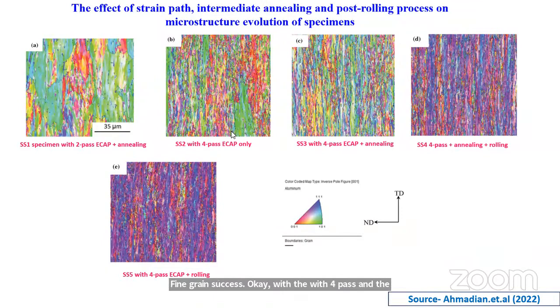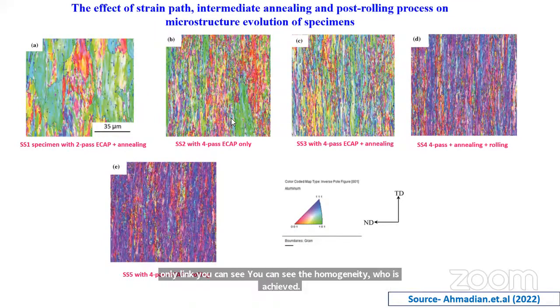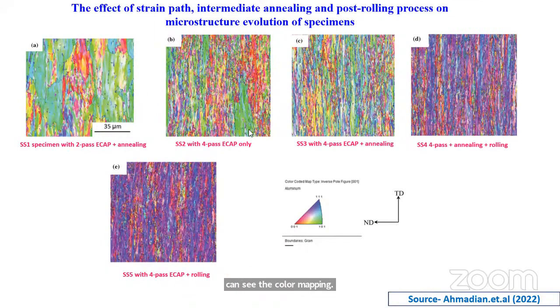With 4 pass and annealing, you can see the homogeneity is achieved. After annealing, you can see the homogeneity in the color mapping. Here a lot of green color is dominant, but in this 4 pass ECAP plus annealing, it is homogeneously mixed.